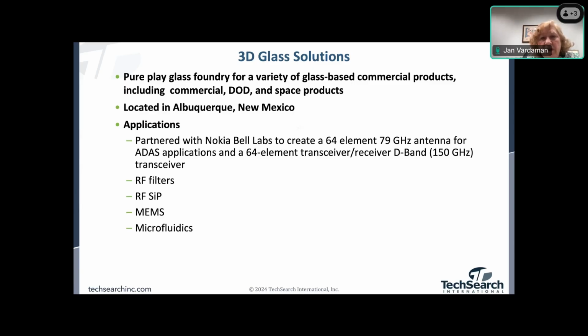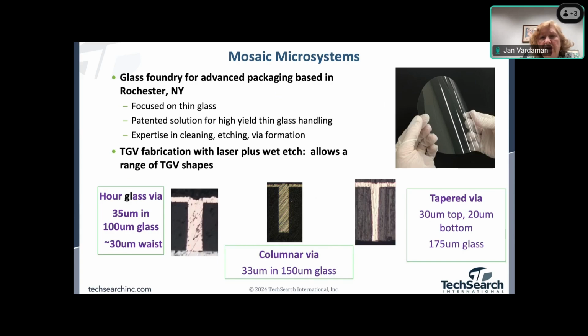Next slide, please. You have the work at Mosaic, which is a glass foundry for advanced packaging based in Rochester, New York. They've really focused on doing things with thin glass. They've got a patented solution for high yield thin glass handling. They've got a lot of expertise in cleaning, etching, and via formation. And then they do a TGV fabrication with a laser plus wet etch to allow a lot of different TGV shapes. So they've demonstrated some things, but mostly R&D, not product at this point in time. Next slide, please.